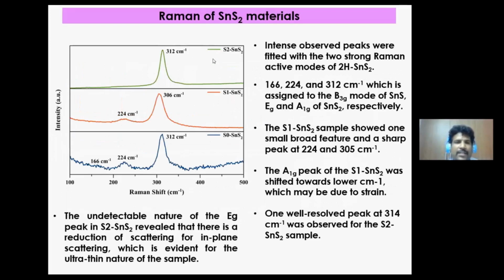Okay. So next, a very interesting study is Raman. With this Raman, we have confirmed the nature of the material, whether it is single phase or multi-phase, and the flatness of the surface. Okay? So we have found the intense observed peaks were fitted with two strong Raman active modes. So mostly tin disulfide was predicted with the 224 and 312 centimeter inverse. So that was observed in all those 3 samples.